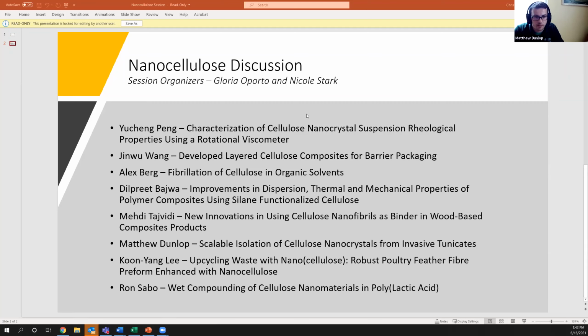I also spent a little bit of time in the presentation talking about some of the ways we've used the CNCs. Tunicate CNCs are unique and distinct from wood CNCs in that they have a higher aspect ratio. They're much longer. And as a result, they can complement wood CNCs in a variety of different applications. And in fact, we've actually gone what I think is a further step where we've looked at combining wood CNCs and tunicate CNCs. The idea being that a combination of high aspect ratio and low aspect ratio fillers together within a common polymer matrix may provide unique properties to the materials that they're reinforced with.